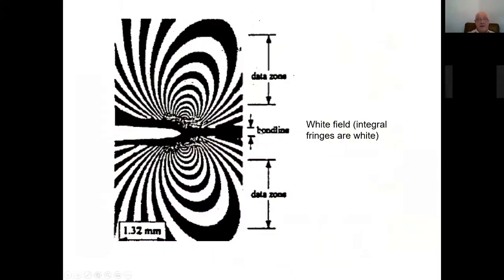And if you even have a higher loading, a blunted crack, as you can see, practically speaking, whatever is in this process zone, zone three, has to be taken out. In fact, we did some measurements for such cracks along a bond line between two different materials, and parallel to bond lines. I'm going to show you some of these fringe patterns. The data zone which is available would be quite further away from the crack tip, so the disturbance given by the bond line is even more significant.